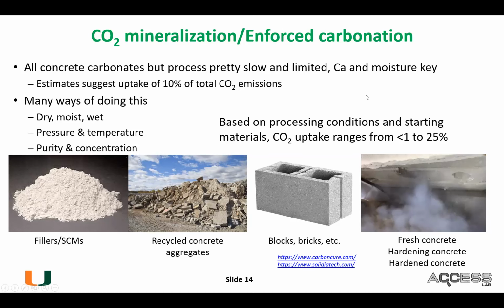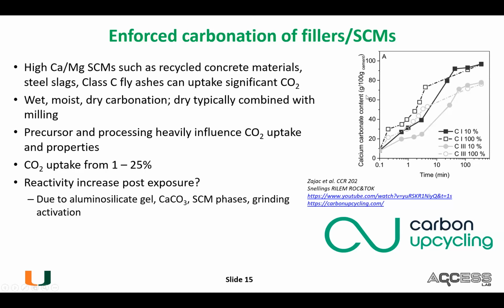Now, the first technology is enforced carbonation of fillers or supplementary cementitious materials. So the same materials I talked about, like fly ash for example, you could just take the fly ash as is, in a powder form, and expose it to CO2, and it will uptake some amount of CO2.